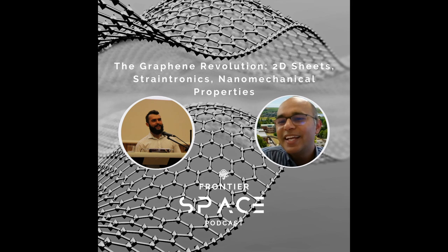We found that the coated region of the graphene is showing friction values nearly 1/10 of the bare silicon. We used a silicon system as the surface, because most robots are made using silicon devices. So this was a benchmark to understand. The fundamental finding is that graphene does not accumulate the frictional energy, the friction-induced heat. It dissipates easily. So your gear system will not accumulate heat. When it dissipates, the whole system becomes durable.